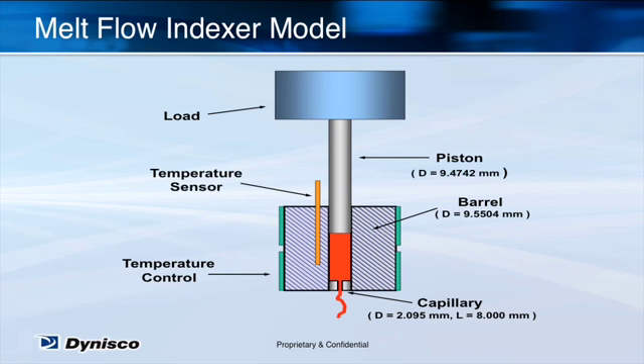with a defined weight. The pressure in psi would be the pounds of the test load divided by the area of the piston in square inches. The weight of the material driven out of the capillary by that pressure in 10 minutes is that material's melt flow index, or MFI. The melt flow index test is a very simple and effective way to check material viscosity.